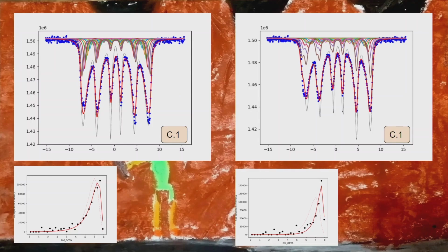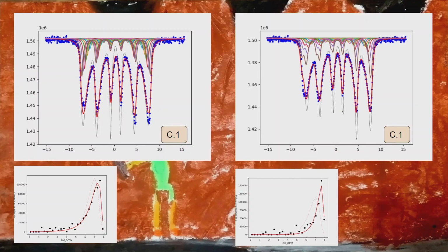However, with other samples, we started to see that it was not possible. So we tried to make a distribution of magnetic fields for two sites, one sextet for the irons in the tetrahedral and another sextet for the iron in the octahedral sites. Both are reduced because the volume of the particle is diminishing in the same way. And the result was different. Here we have a good fit here and not so good here. In this case, we have better here and not good here. So there is a mixture.